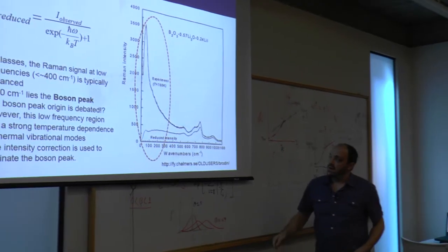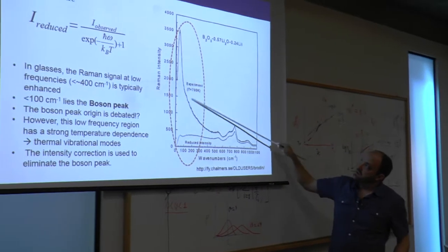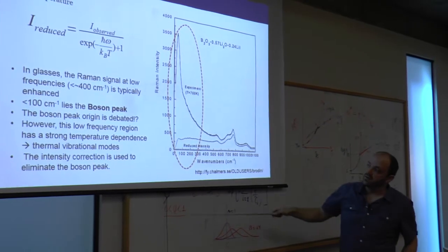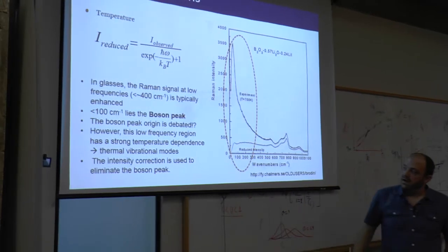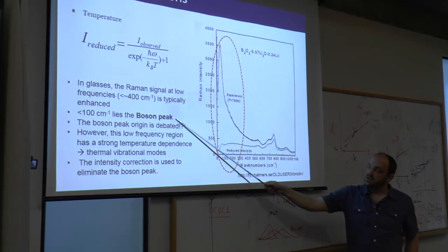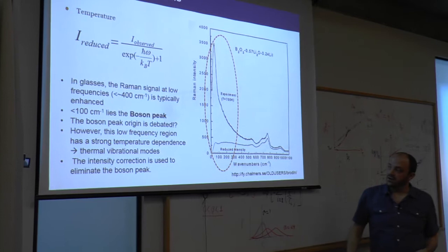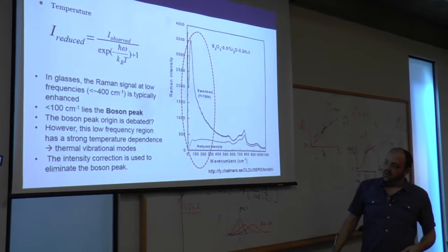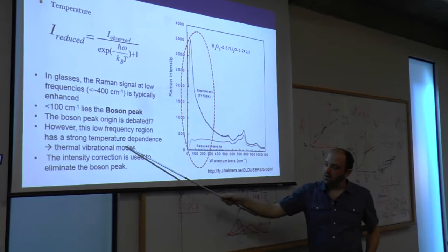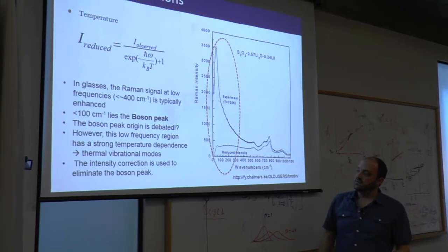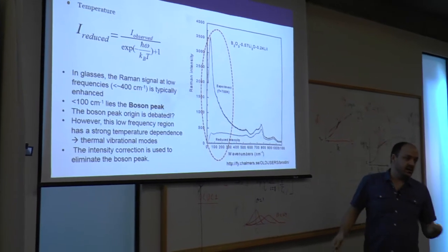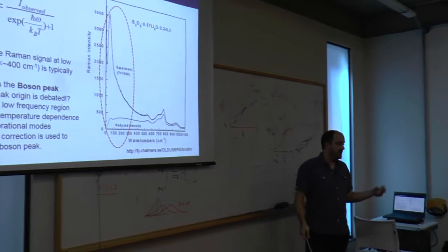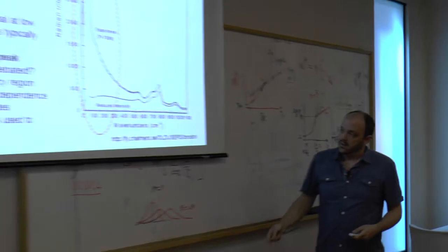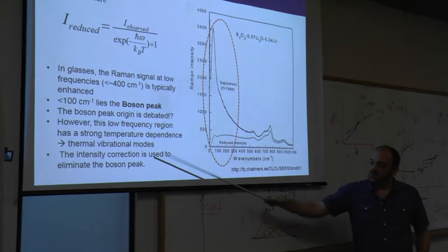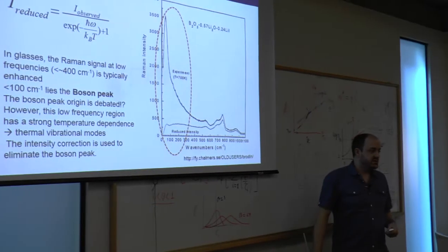Fast forward through some time and getting better equipment, and we see that this peak is actually a real thing. It's called the boson peak. Its origin is debated, and I'm not going to get into that debate here. But it has a really strong sensitivity to temperature, and you can actually use this to back calculate to 0K and look at the intrinsic disorder of your sample. So this intensity correction was used to eliminate essentially what is the boson peak.